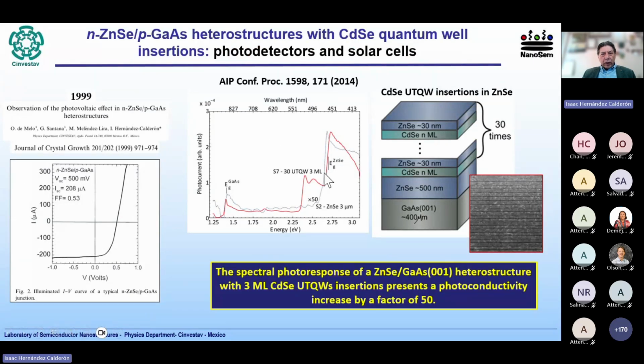There are many applications for these ultra-thin quantum wells, for LEDs, lasers, and others, but among other interesting applications, one is that we can insert these ultra-thin quantum wells in an n-zinc selenide p-gallium arsenide heterostructure that can be used as a solar cell, and by the insertion of these cadmium selenide ultra-thin quantum wells, we can increase the spectral photoresponse by a factor of 50. That was a very interesting result. So the ultra-thin quantum wells, here's an electron microscope picture, can enhance the trapping of photons in a very impressive way.